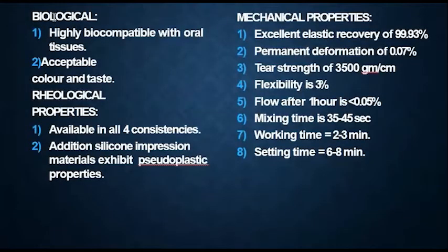Now coming to the properties of addition silicone, it is highly biocompatible with oral tissues. It has an acceptable color and taste, and it's available in all consistencies, and it has pseudoplastic properties. And coming to mechanical properties, it has an elastic recovery of 99.93% when compared to others, and a permanent deformation of 0.07% occurs, has a tear strength of 3,500 grams per centimeter, and flexibility is 3%. It has a mixing time of 35 to 45 seconds, working time of 2 to 3 minutes, and setting time of 6 to 8 minutes.